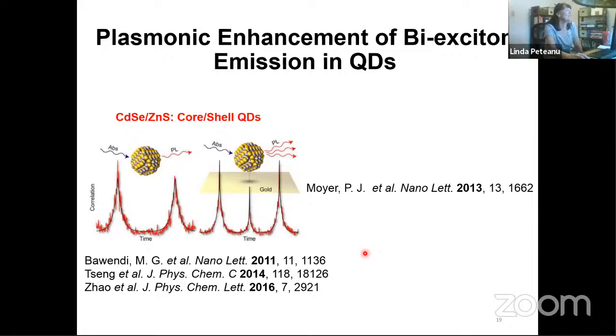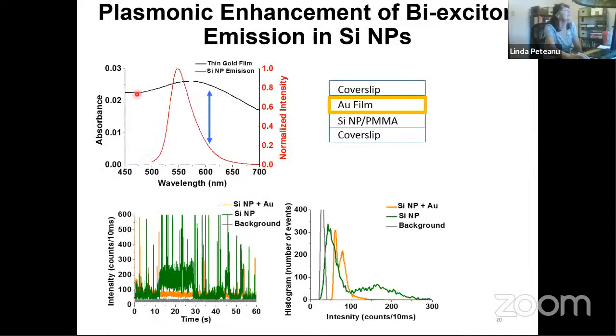there are other ways in which we can think about how we can support this assignment. There have been a number of reports in the literature that interaction with gold surfaces can cause semiconductor quantum dots to show preferentially biexciton and multi-exciton emission versus the same properties on glass. And so we effectively did that experiment ourselves with a thin gold film and our nanoparticles there.